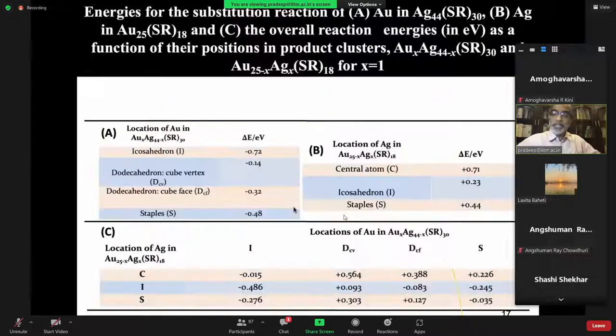Now, you can do computations. Even without computation, one would say that if you take gold and put silver into that, the energy is going to be positive because silver is less noble, and this cluster system wouldn't like silver getting in to make it less noble. On the other hand, if you take silver 44 and put gold into it, whether you put it into the I or DCV or DCF or S position, everything is going to be negative.